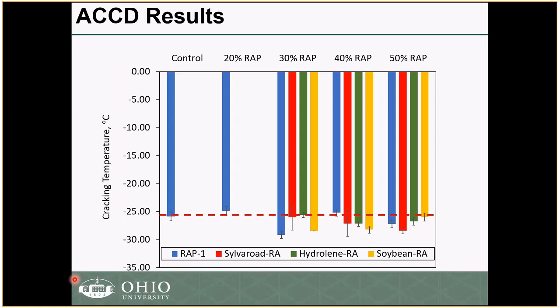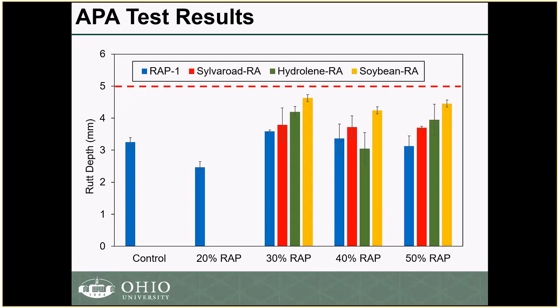So the virgin asphalt binder will have an important effect on the low temperature cracking of your mixture. And again, the recycling agent, the same thing, we're able to get the same low temperature cracking as that of the control. So both are good.